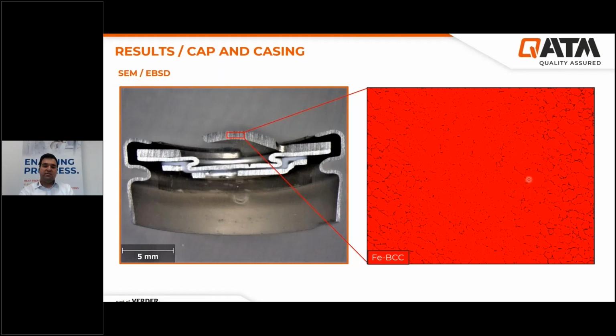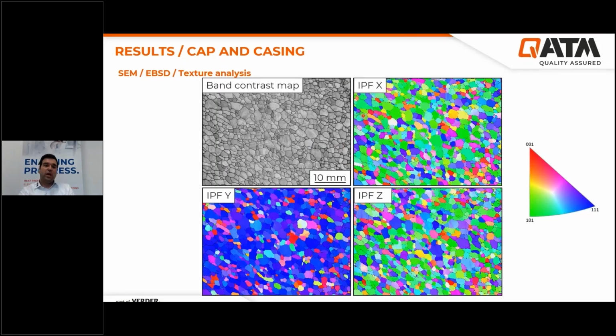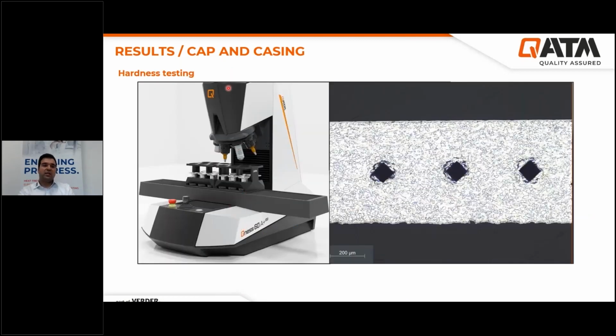At first, we have done the phase analysis, and we can see that here in the cap of the battery, we have 100% iron BCC structure. Also with EBSD, we can do the texture analysis. It means that we can do the inverse pole figures in different axes, in X, Y, and Z axis. And as we can see here in the Y axis, we have the preferred structure. It means that most of the grains have the direction of 1, 1, 1. And as you can see here is a preferred direction of the grains in the inverse pole figure in the Y-axis.